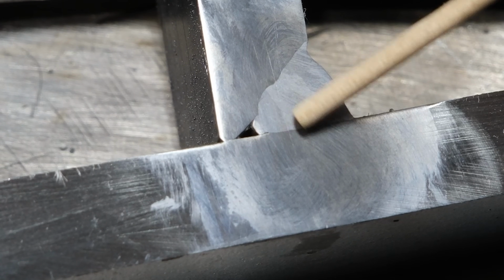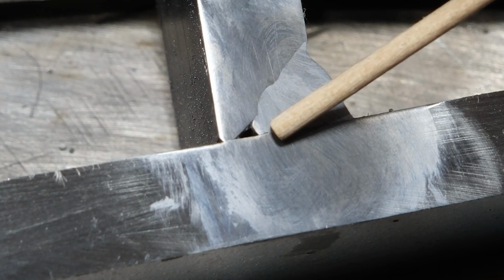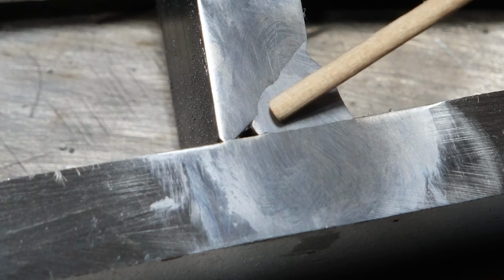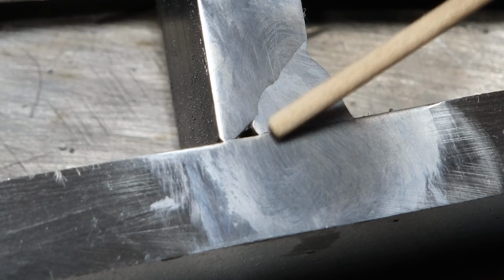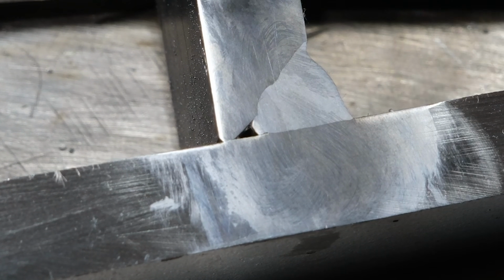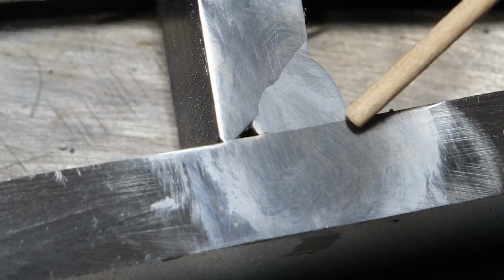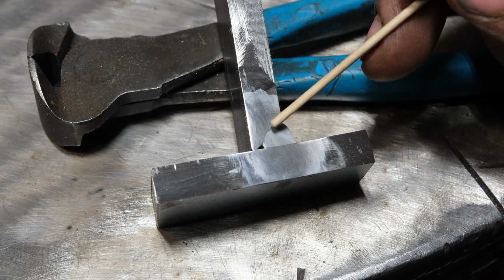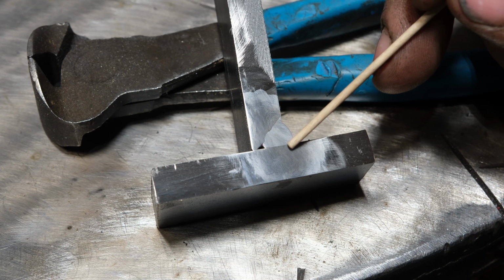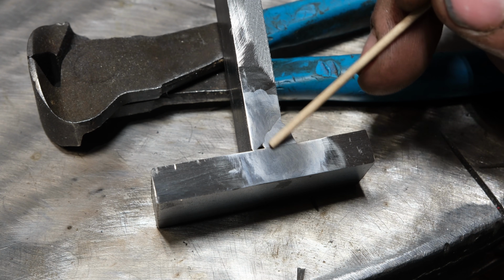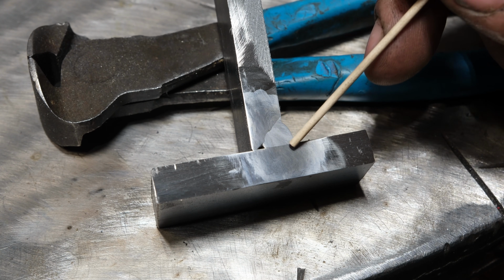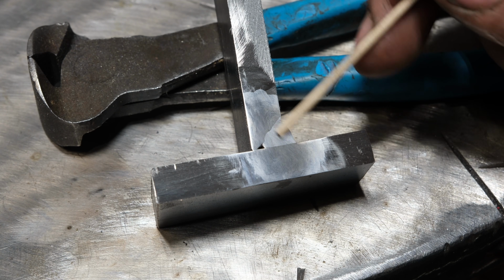It looks like a crack. It basically is just sitting on that plate. That gives a great place for a weld to start tearing at when you have that. Very undesirable. So based on what I'm seeing here, although it breaks at a fairly high strength level, this beveling is no solution to gain fusion beyond a certain point, so it's not a cure-all.